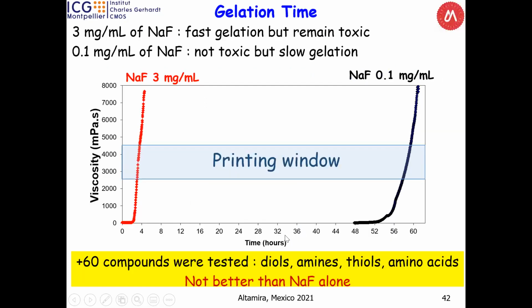I would like to explain why we need to control the gelation time. As you suspect, the idea at the end is to be able to print this hydrogel to make a shape for implantation, for cartilage, for example. You can make an injection, but sometimes you open and you make some implantation. You need some form of this hydrogel. So with 3 milligrams, it's highly toxic. 0.1 is not toxic, but it's very slow. The idea is to find the catalyst and co-catalyst to be in this window. Even here, it's not a problem, but not so fast.